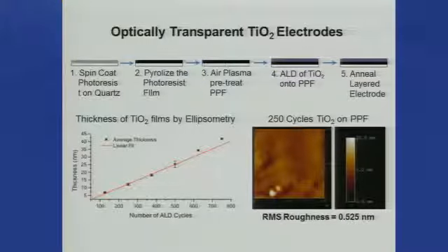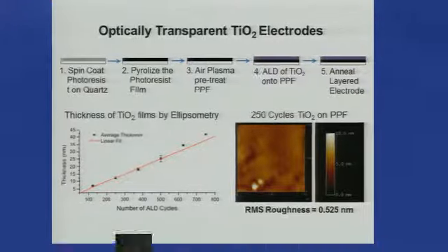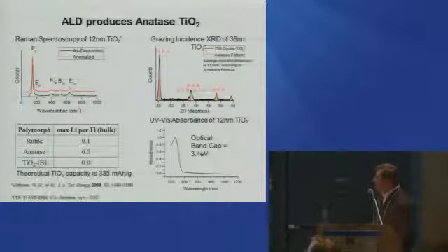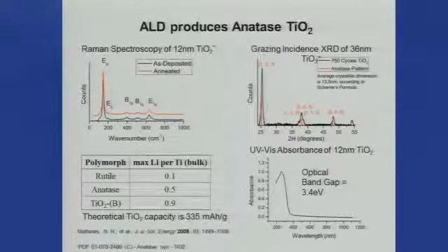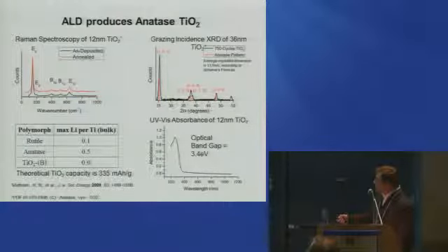In our case, our focus is really to grow a stable TiO2 layer that's very thin so that we can study the thickness dependence of the lithiation of this material. If you get this right, you can actually make phase pure anatase. You can't make phase pure TiO2B. I wish we could get that to work. But with all of the particular things that we do to try to understand the structures, we could do Raman. In particular, if you look at XRD, you get nanocrystalline anatase. Roughly the average crystallite dimension is about 13.5 nanometers. Therefore, the optical gap of this is actually larger than what you would expect for large crystalline TiO2 anatase. So there's a confinement effect.